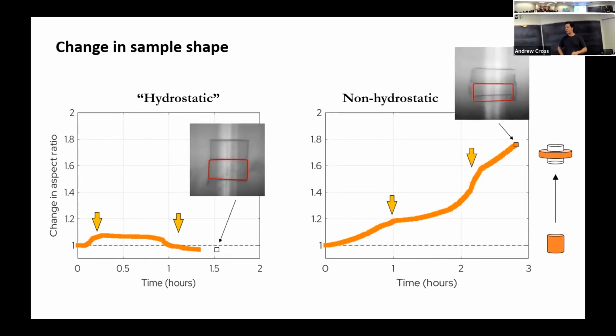Now, in our non-hydrostatic case, on the other hand, we're getting constant flattening just because we're squishing the sample. As we go through the phase transition on the way up from quartz to coesite, we get a small increase in flattening. But then we get a big increase in the amount of flattening as we go back down through pressure. So the sample's getting bigger and it's expanding outwards this way. So we measure quite a lot of flattening, as you can see in the comparison of the radiograph with the initial dimensions. This is our anisotropy that we're looking for. That's one indication that we've got transformation plasticity type things going on, as well as that 2 order of magnitude weakening that we saw in differential stress.